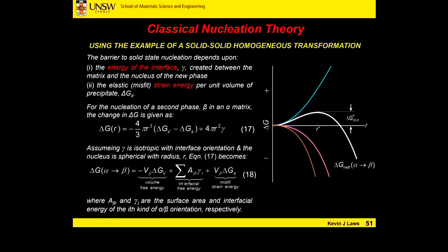So we've seen a few examples where we get precipitation of a new phase from an existing phase when we change temperature based on the stability of that phase, or even recrystallization. So basically all things here are similar to the solid-liquid case, apart from the fact that we've now got an additional term to deal with the interface energy from the solid to the solid. There's an additional factor here, and that's based on lattice mismatch. So we'll go through the slide.